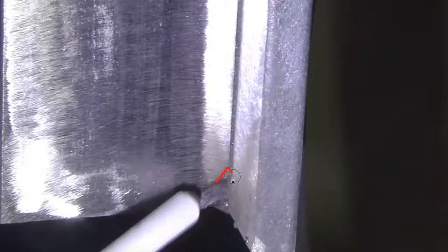Now 140 amps is on the low end of the range for 5/32 7018. If we were using 1/8 rod, the range would be pretty wide. You could probably go as low as 100 and as high as maybe 135, and you could still do a good job. You still avoid undercut. You probably would still have a little arc blow toward the end of each rod.